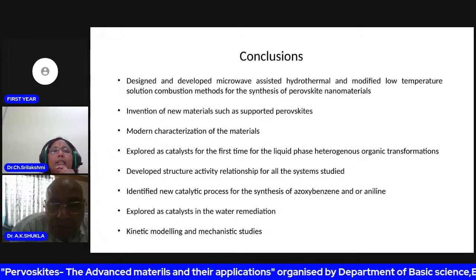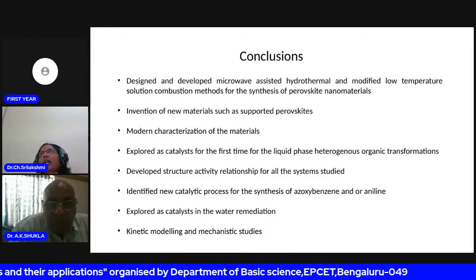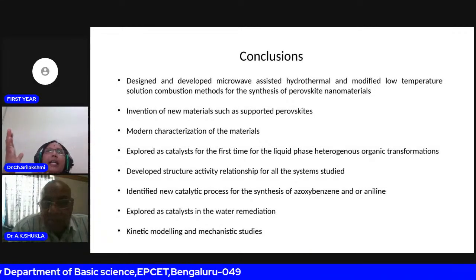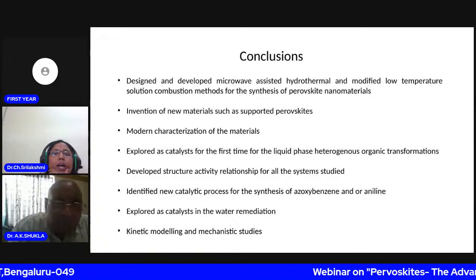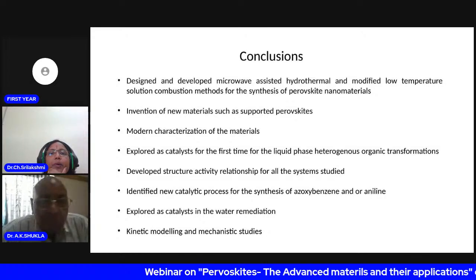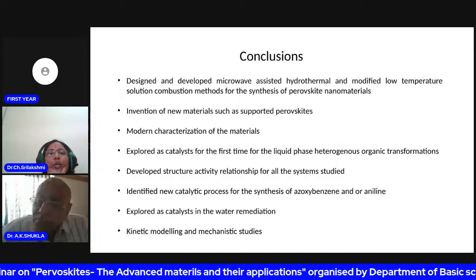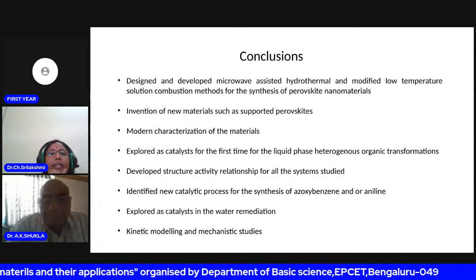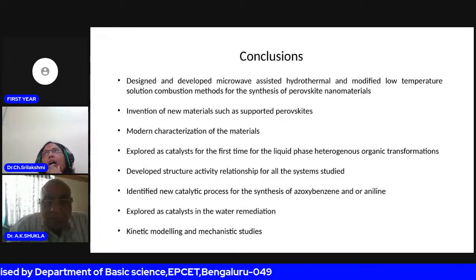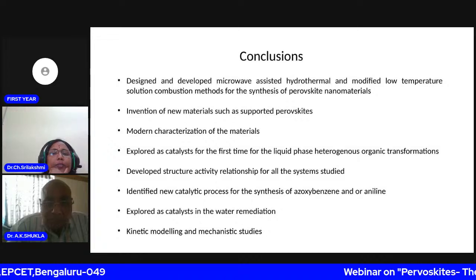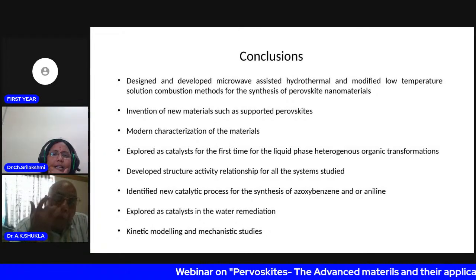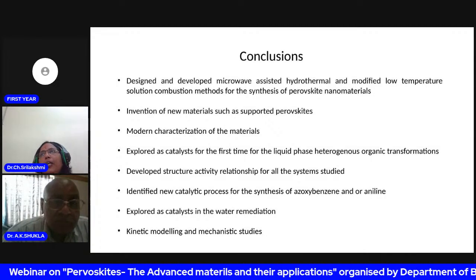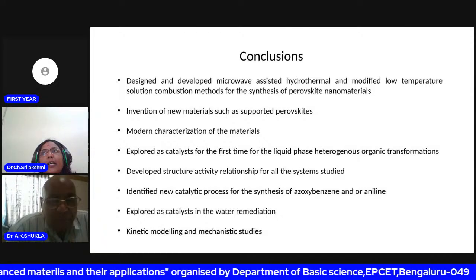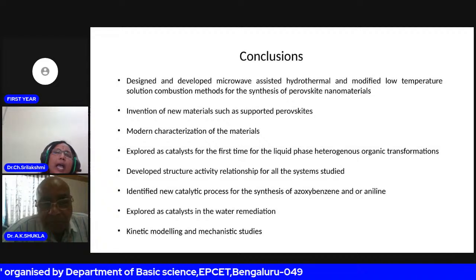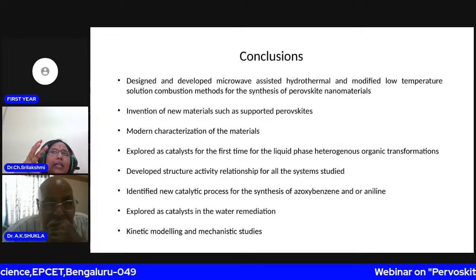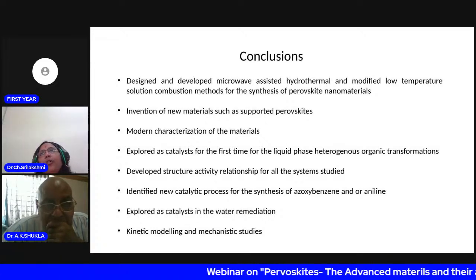And in every study I did, I always tried to develop some structure activity relationships. What is the structure and how does this impact the catalytic activity of this material? So always I developed a structure activity relationship for whatever materials I studied, and identified a new catalytic process for the synthesis of azoxybenzene and aniline, and explored catalysts in water remediation, which is the degradation of nitrobenzene, and almost all the things which I just presented for photocatalytic degradation, kinetic and mechanistic studies. Two papers are under review now, where I use perovskites for the degradation of chloroorganics, and another important application is I dispersed this perovskite nanomaterial in a polymer and used it for the cleaning of oil in water.